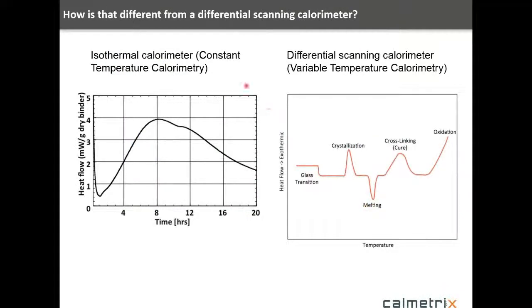A question that always comes up is, well, I have a calorimeter in my lab. How is it different from what I've got? On the left is the typical data that you get from an isothermal calorimeter. So here we're looking at heat flow as a function of long time frames. And over on the right is typical data from another very common calorimeter that you might be familiar with, and that's a differential scanning calorimeter. These instruments are both the same in the sense that they both measure heat flow as a function of time or temperature, but that's where the comparison stops. They're really used for totally different applications.